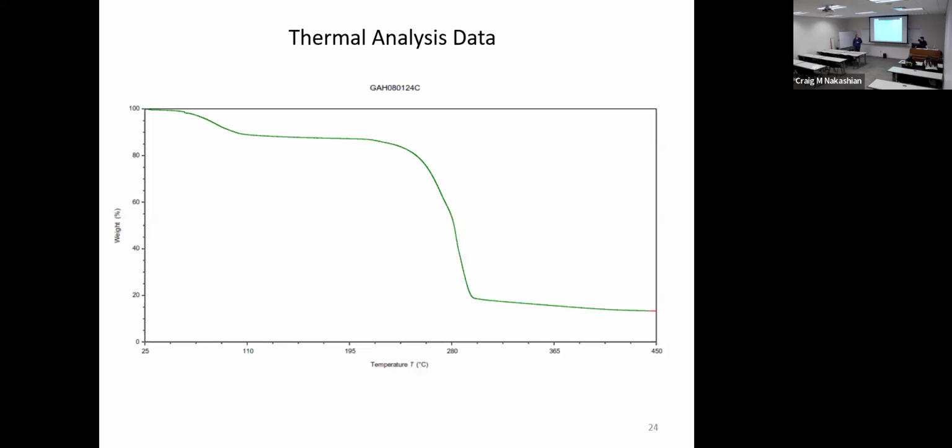Okay. And then we have a divot at the top again, the gas molecule is leaving, and as temperature increases more, the structure starts to degrade. We just left off the derivative, but you would see that again, you can identify a huge loss early on because the size of benzyl alcohol or chlorobenzyl alcohol is extremely large. But again, the pattern of everything is exactly the same, that we're generating the loss and degradation of our framework well after 220 degrees Celsius.